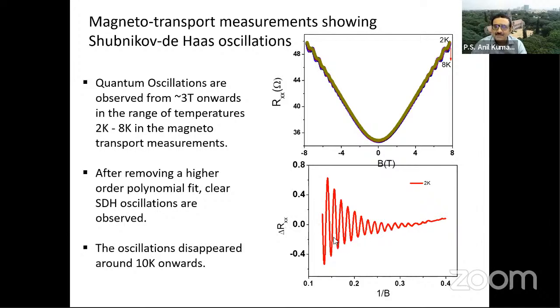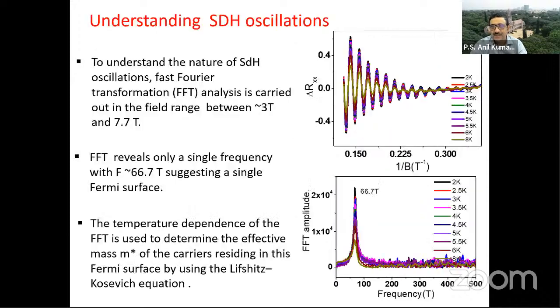This tells you something about the quality of the material. You get nice oscillations starting from 3 Tesla, and in the temperature range 2 to 8 Kelvin. Now, once we have these oscillations, we can extract several parameters about the system, which were unknown in the past. So the first thing is that we have to understand the SdH oscillations. Henceforth, I will just call them SdH oscillations.